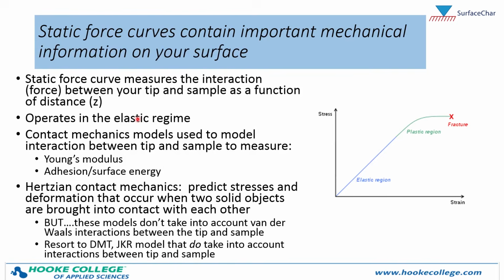So these static force curves do contain important mechanical information on your surface. The static force curves are measuring the interaction or force between our tip and sample as a function of z. These static force curves are operating in the elastic regime between our tip and sample. So if we map the stress and strain for an idealized crystalline material, what we can see is as we pull on the material, initially, we have a linear relationship between the stress induced and the strain, or displacement or deformation, resulting from it. That linear relationship, that linear coefficient, is what we call the modulus. And again, that's the elastic regime.